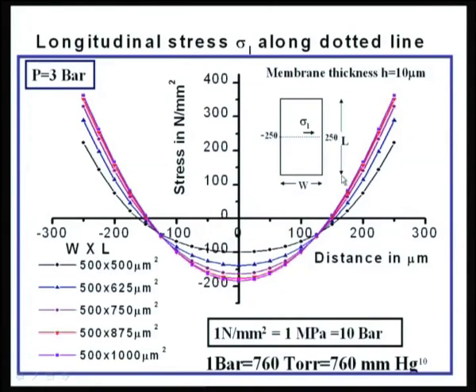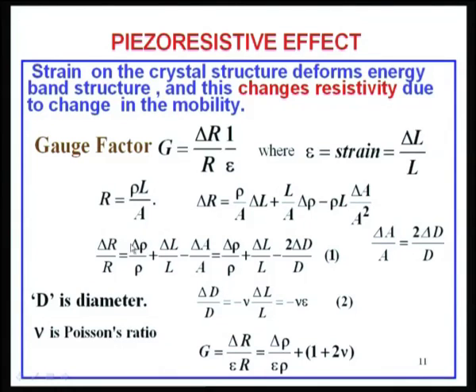if you keep the width constant and if I keep on varying the length of the membrane, the stress concentrations all through will increase. For example, if I make it double, width 500 micron, length 1000 microns, the stress will actually become much larger than that. You can see it goes up from 200 newtons per millimeter square to about 350. Same way here, the compressive stress also goes from 100 to about 200. Okay. Now, the definitions.